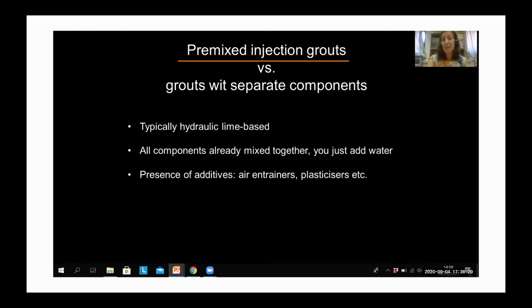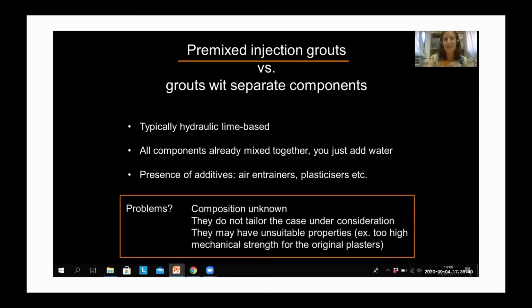However, there may be some problems. I'm not saying that these are always better to use, but we need to take into consideration that there are some problems. So for instance, the composition is unknown. You have a description on the technical data sheet, but it's rather vague very often. And as very often in general with conservation materials you buy, the exact composition is not disclosed basically.